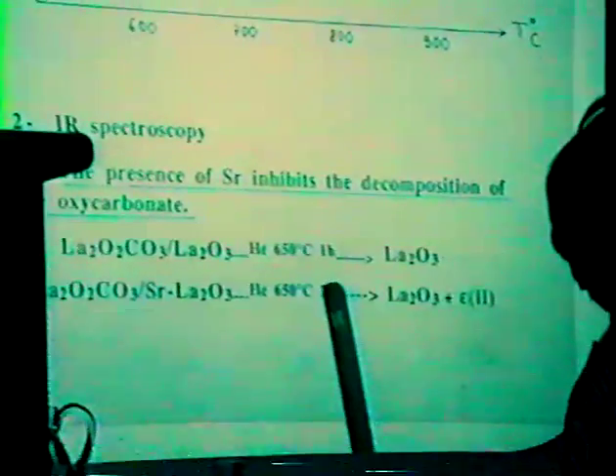The addition of strontium inhibits the decomposition of the oxycarbonate, and this increase in the stability of the oxycarbonate gives, as I told you, increased selectivity.